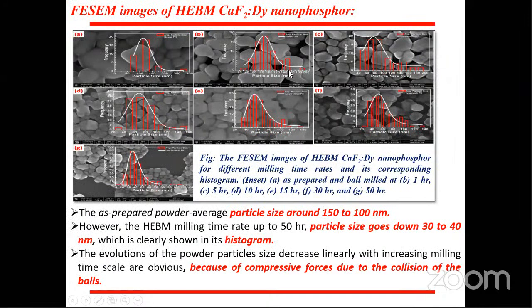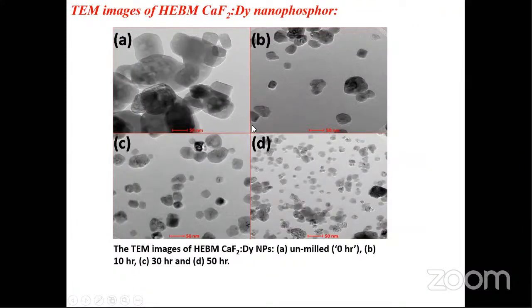We also confirmed using FESEM for size determination and morphological behavior, and we got a particle size of around 30 to 40 nanometer for the 50-hour sample, and around 150 to 100 nanometer for the pristine sample. Pristine sample means 0-hour milled, prepared by the chemical co-precipitation method. These histograms indicate the average particle size. We also confirmed using the transmission electron microscope, but I will skip that due to time constraint.